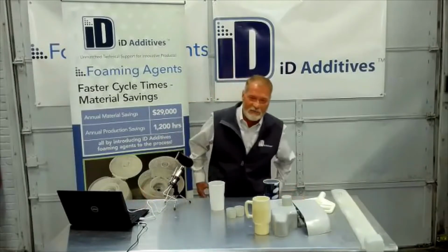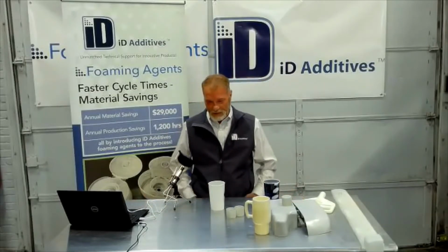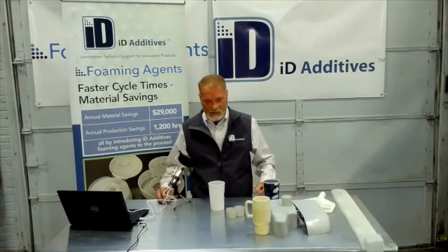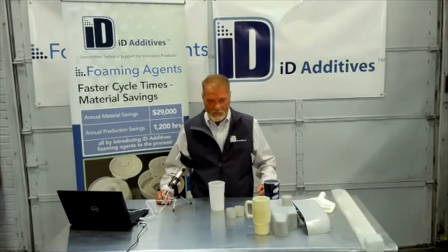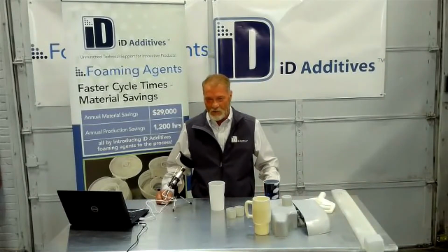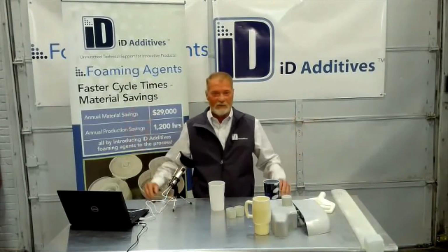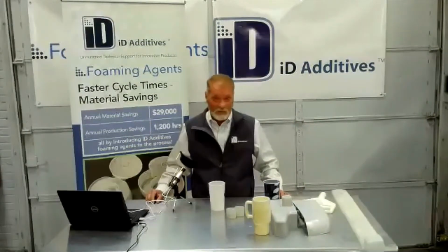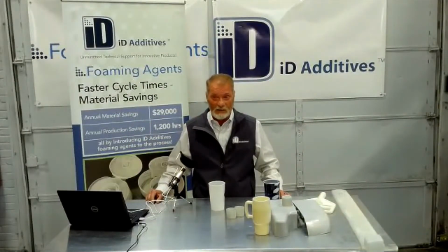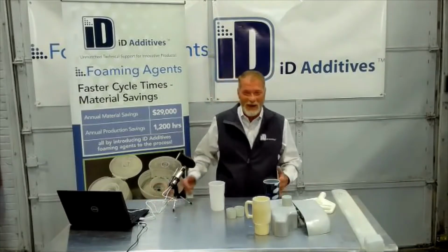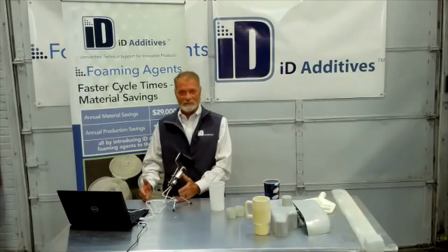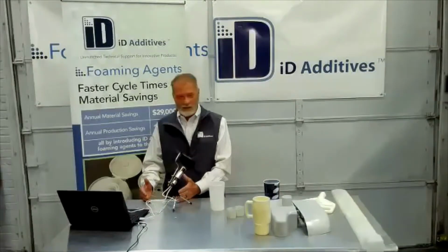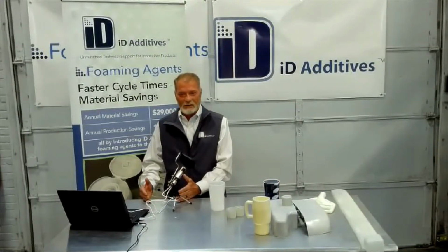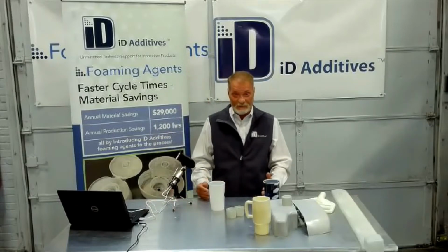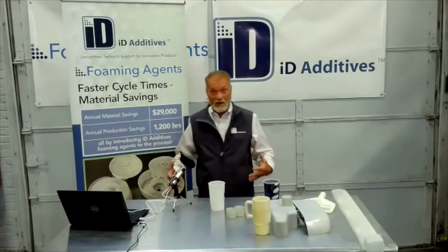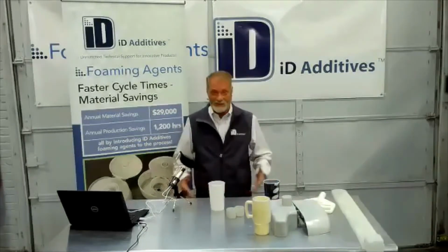And when you add foam, I had a customer running Xenoy, which is a pretty tough material for them. They couldn't fill the rib. They added foam. All of a sudden, the rib filled. So it will open process windows up. It will improve flow. And if it does that, now you look at your temperatures, right? If foam changes the viscosity of the material, there's only one other thing that does that, and that's heat. So now you have to ask yourself, do I need the heat now that I'm adding foam? Do I need heat? And you don't.